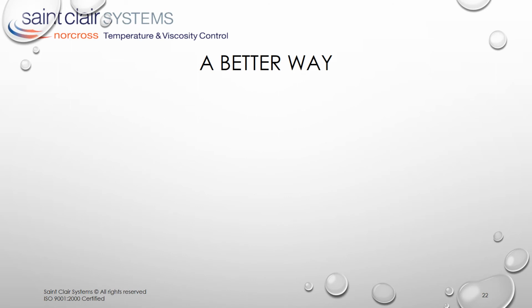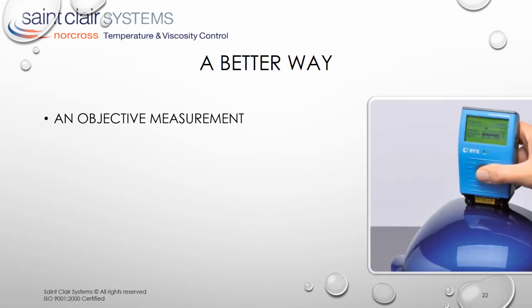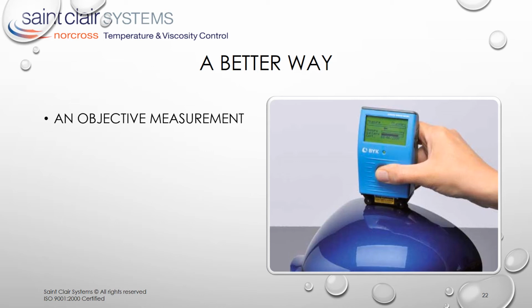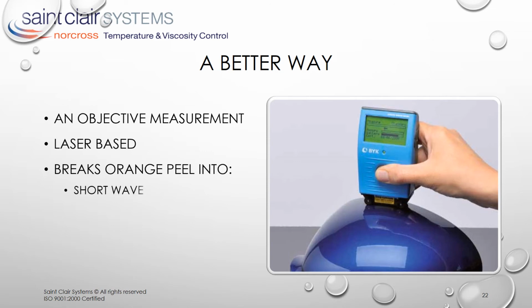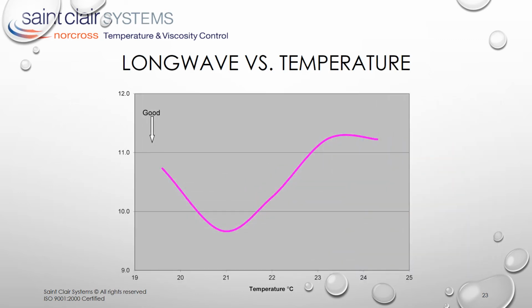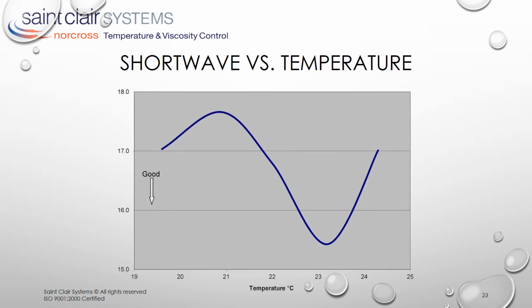But as engineers, we needed a more reliable number, a more objective number, one that's not dependent on an operator or the available light. Enter the BYK wave scan. This handheld gadget uses laser light to measure the variations in the surface finish. It breaks them down into two components, short wave and long wave, and their relationship with temperature is very interesting. Here we see the optimal long wave performance at approximately 21 degrees C. And here we see the optimal short wave performance at just above 23 degrees C.